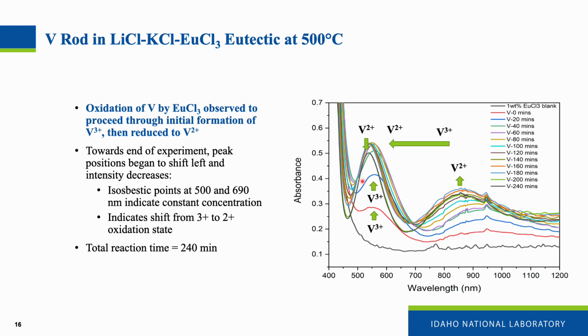And this is only possible spectroscopically, because if we just look at the salt and do some post corrosion analysis, we will only see maybe just how much vanadium is present. We can't even tell what oxidation state that is. And using an in situ technique like this, we can actually see the different oxidation states that are forming. So this gives us a little bit more insight on how the process is happening.